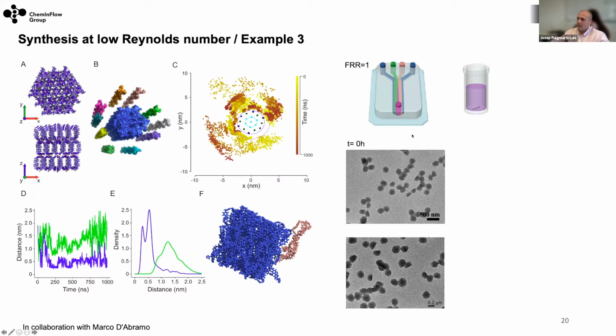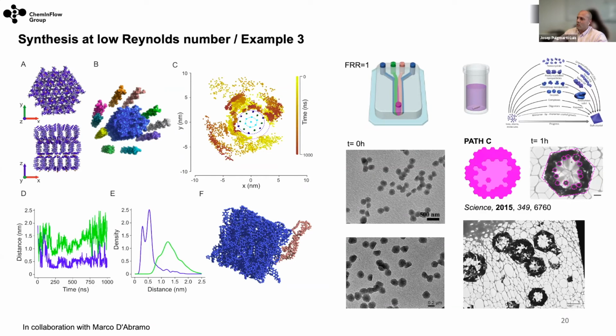But then we also tried to isolate the nuclei in this crystallization process. What we observe is that at time zero with the microfluidic device, we could achieve these small particles, so we could isolate them, whereas in bulk it was not possible. We always had empty TEM grids. But here, we were astonished when we observed that. What you see there is this pathway that I presented in the mesoscale assembly. We have the formation of hexagonal particles that are all self-assembling to generate the final thermodynamic product. So this is a clear example of mesoscale assembly on a functional, in this case, spin crossover compound.